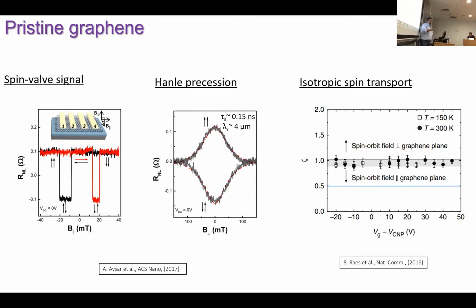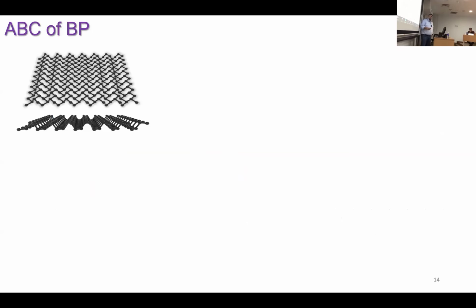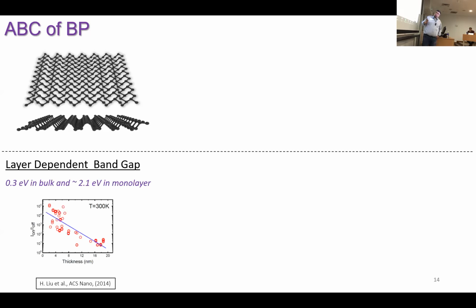So I will show you that this is completely different for black phosphorus. So let me briefly say why black phosphorus. This is a semiconducting material, and you can thin it down to again a monolayer. And the material has a very strongly thickness dependent band gap. For example, the bulk of black phosphorus has a band gap of 0.3 eV. In monolayer it's like 2.1 eV. So basically with that you can control many charge properties and on-off ratios of the transistors, etc.